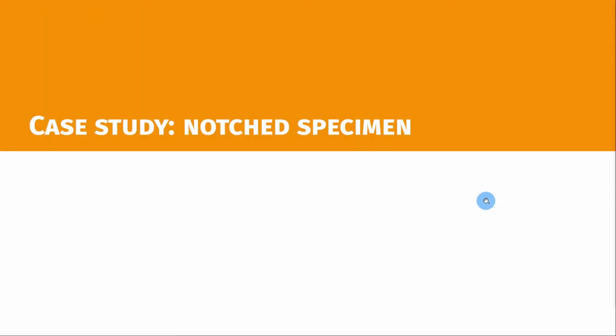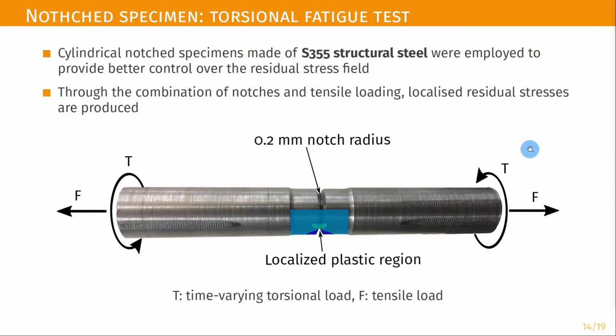I will present now an ongoing project that tries to reproduce the difference between pure bending load and pure torsional load in a more controllable environment. For this purpose, notched cylindrical specimens made from the same structural steel as the welded joints were investigated. By means of an axial torsion test bench, a three-axis stress field can be established in the notch. By controlling the axial preload, the magnitude of these stresses can be changed and different loading scenarios can be investigated.